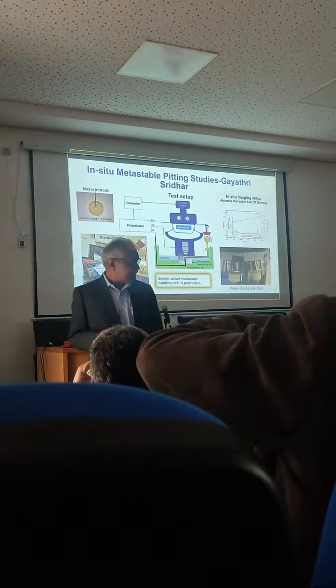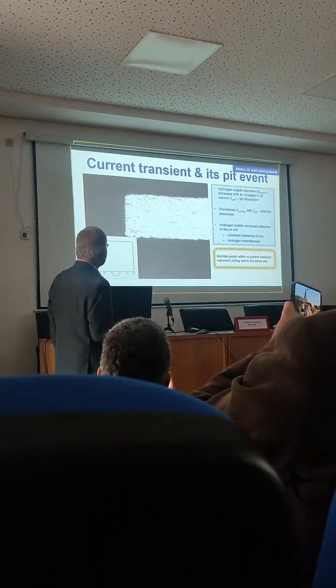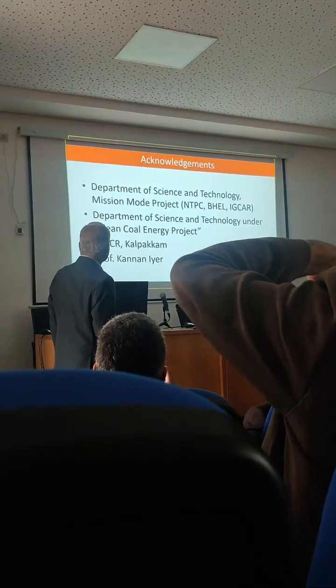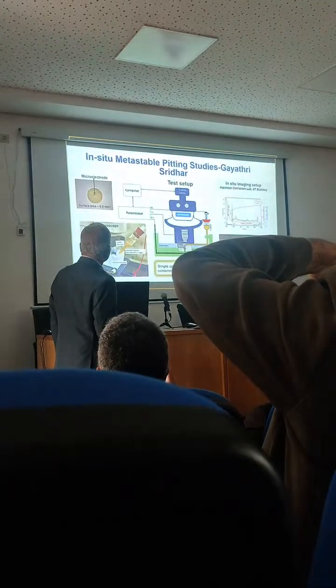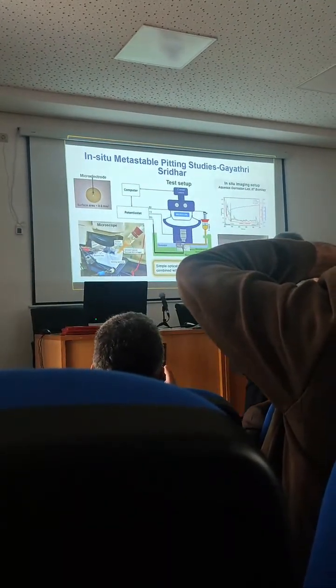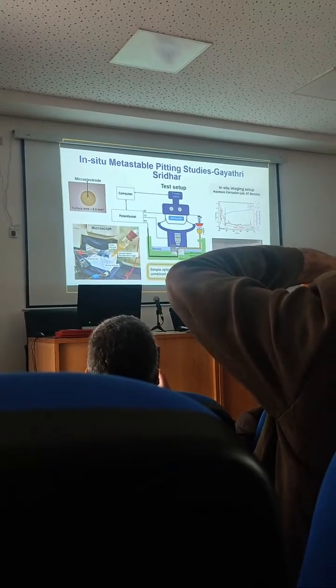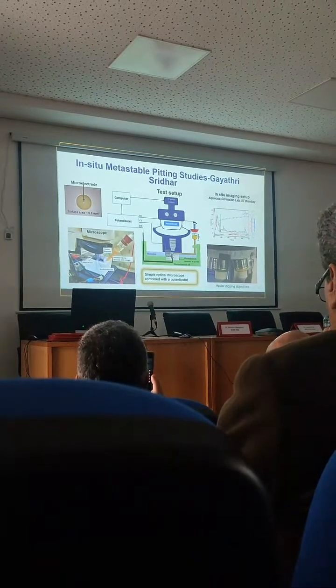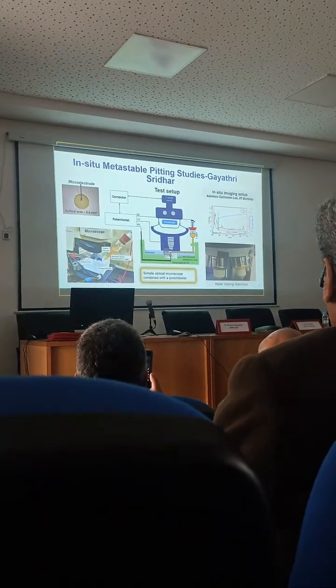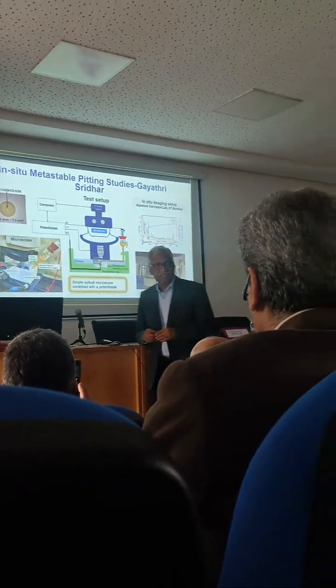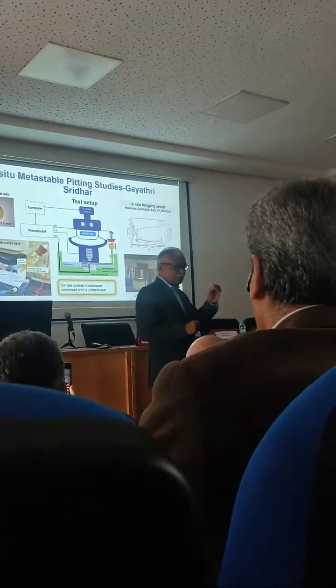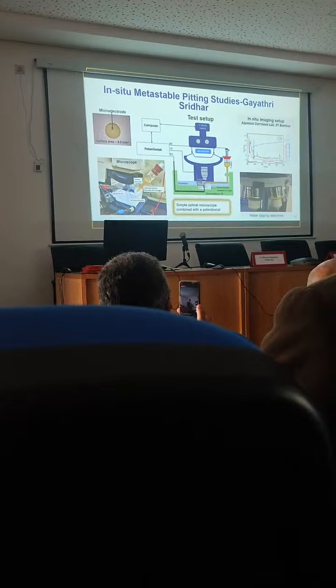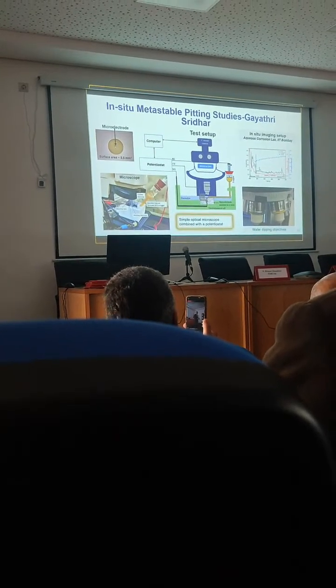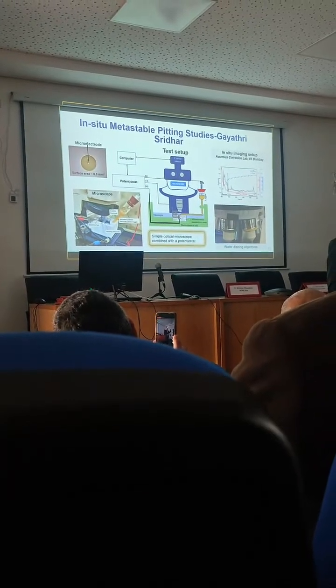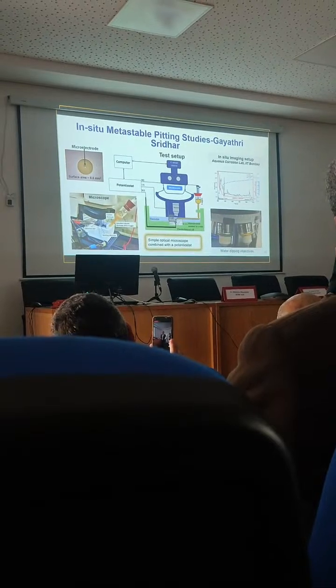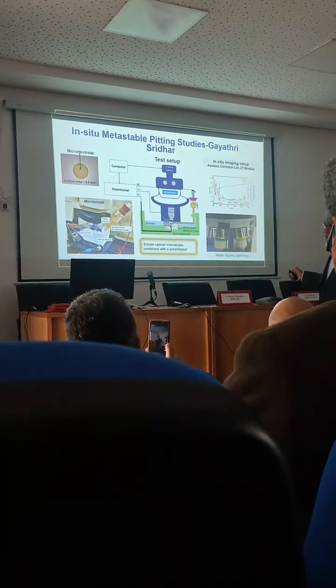And we also looked at something very fundamental here. Okay, let me go here. I think I have not put that here. Yesterday, one of the faculty members talked about fatigue problems in aircraft. When you have cyclic loading, the metal fails, right? So fatigue, stress concentration, you have heard of stress concentration. When you have a pit, we talked about a notch yesterday, the pit becomes a stress concentration, and the crack starts at that location. So pitting is the major reason for that.